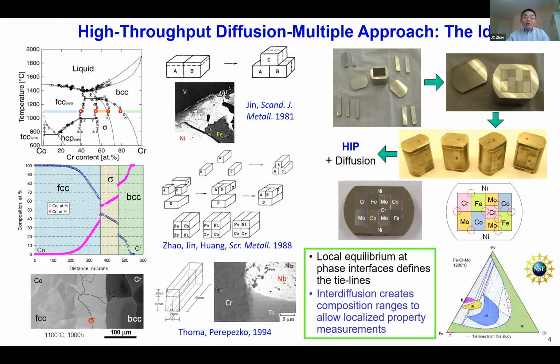Okay, but there's one thing that I thought, this is around a little more than 20 years ago. So if we can take advantage of the composition gradients and have localized property measurements, then we can establish composition dependent properties without making individual alloys. That requires high spatial resolution measurement technologies. So I spent a lot of time developing those technologies. I'm going to talk about that later. But at the beginning, I'm going to focus on phase diagrams and diffusion coefficients that can be extracted out from the diffusion profiles. So there's a binary diffusion couple.